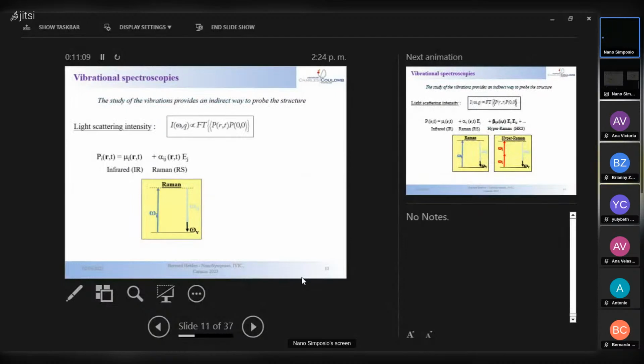Okay, so what kind of optical spectroscopy can we use to do this job, to measure the frequency of this soft mode? So if you look at the light scattering, the light scattering is a Fourier transform of the correlation function of the polarization P of the material. And the polarization P can expand in terms of the dipoles. Mu is the permanent dipole, and this gives you the infrared activity. And at the first order, the induced dipole, alpha times E, gives the Raman intensity, and then the Raman is a two-photon process, where one incident photon is scattered after interaction with a vibration in the media.